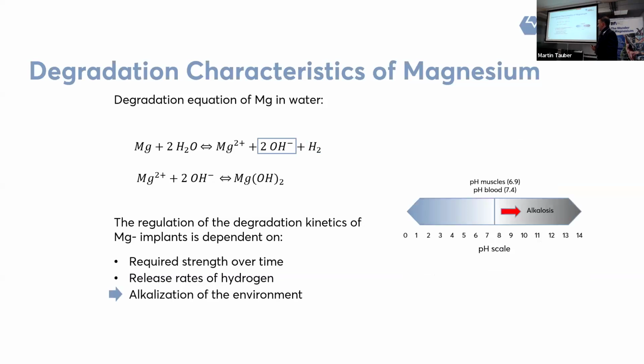However, a third effect that happens when magnesium degrades is a shift in pH. As magnesium degrades, the pH will rise, and a local alkalosis will be the case. Luckily, the physiological system of humans is quite effective when it comes to unwanted pH rises. There are some physiological buffers available that will immediately fight against this pH rise, so there are usually no concerns in this manner. And what's interesting is that bone healing usually relies on higher pH levels. So this reaction will potentially also support the bone healing, as osteoblast cells are motivated to build up bone again.